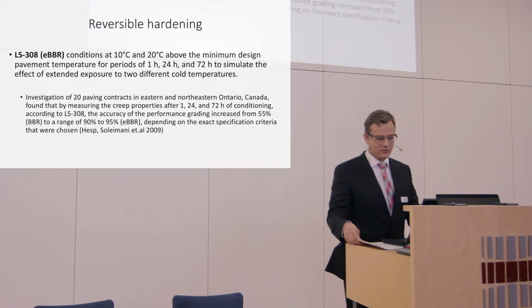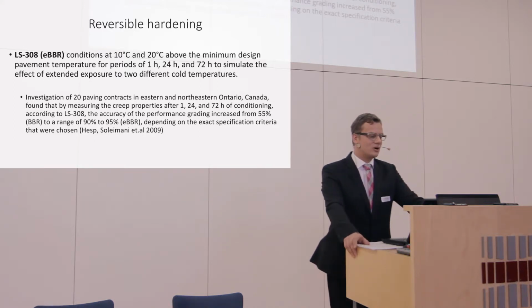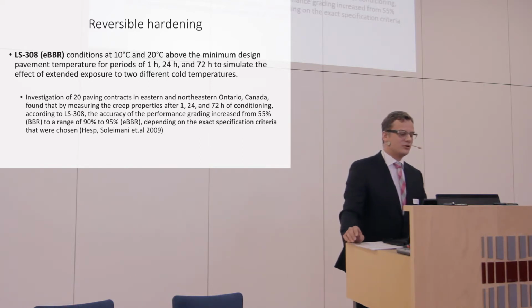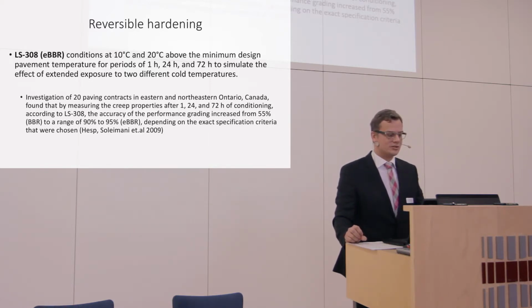First of all, it's extended BBR, or LS-308 in Canada, as they call it. With this, they condition bitumen at 10 and 20 degrees above the minimum design pavement temperature for periods of 1 hour, 24 hours, and 72 hours, to simulate the effect of extended exposure to different cold temperatures.